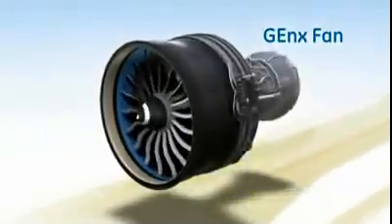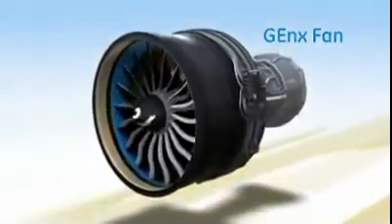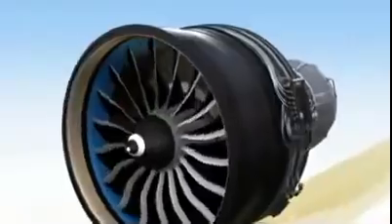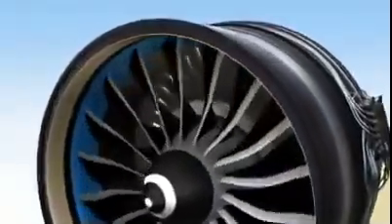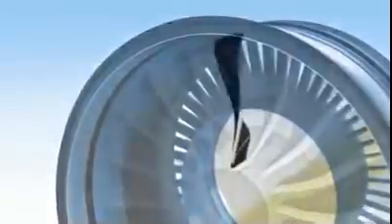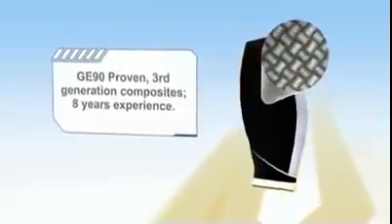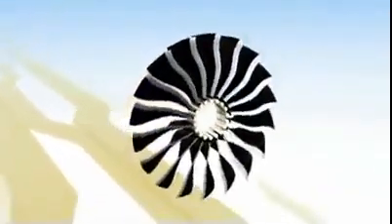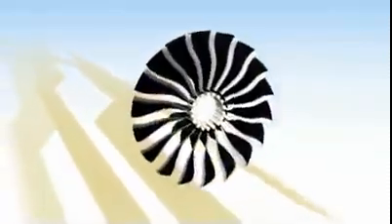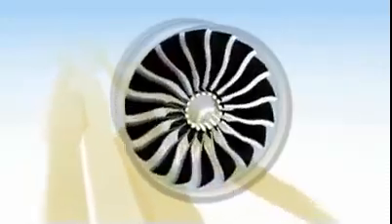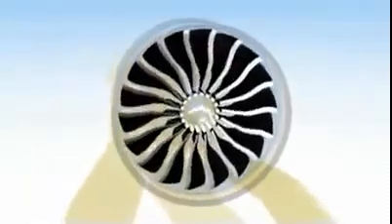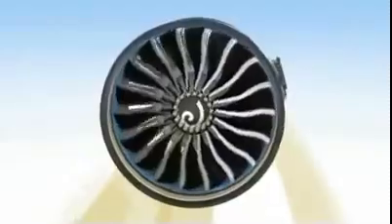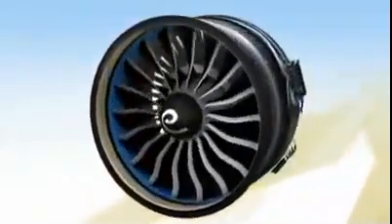Many of the innovations on the GENX are hidden deep inside, not so with the fan assembly. Here, you can see two of the engine's most important and most distinctive features, its composite fan blades and case. The blades are the third generation to be made of carbon fiber composite material combined with a titanium edge. They are so durable that only three have been removed from service in the first six million flight hours. In addition, they are very light in weight and are more fatigue resistant than titanium at less than half the density. Because these composites are extremely strong and can be intricately formed, each blade can be made larger and more aerodynamic. And since they move more air, only half the blades are needed.